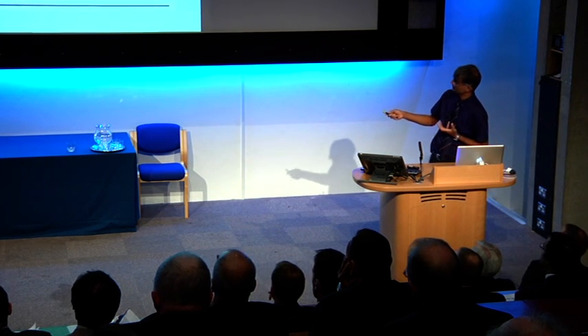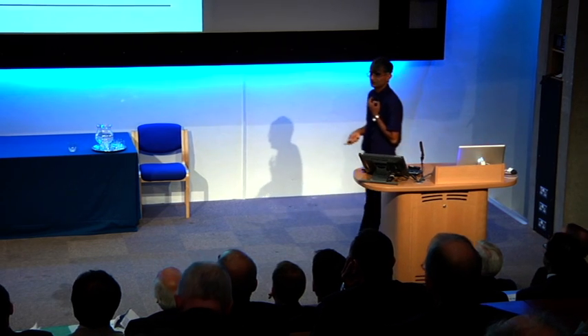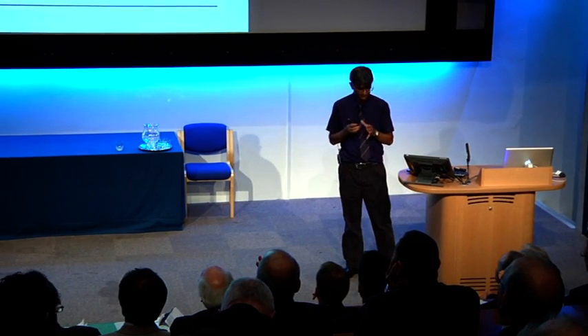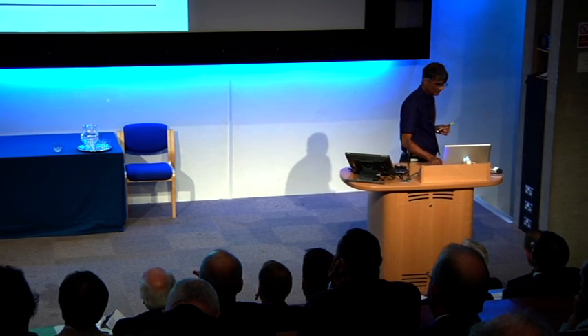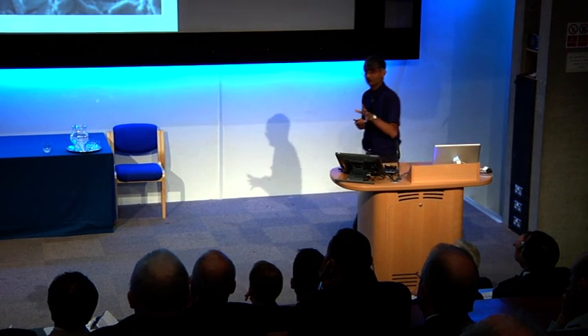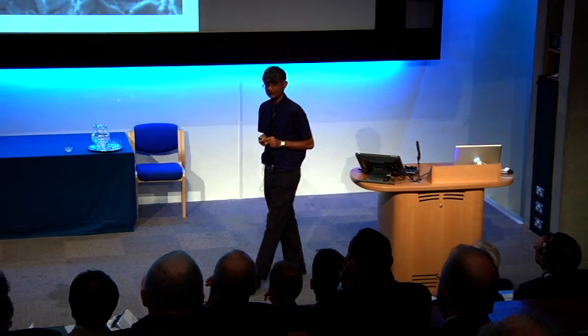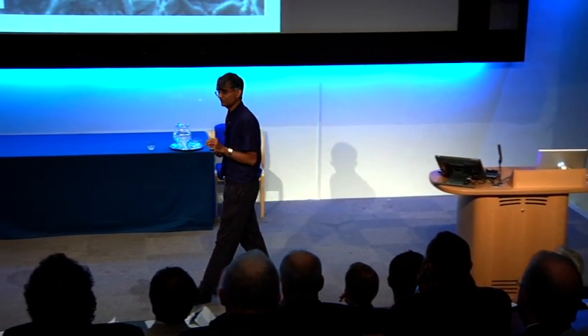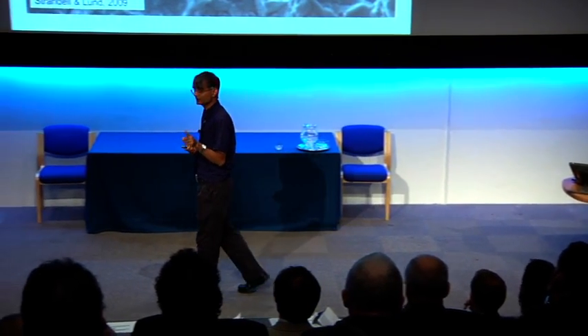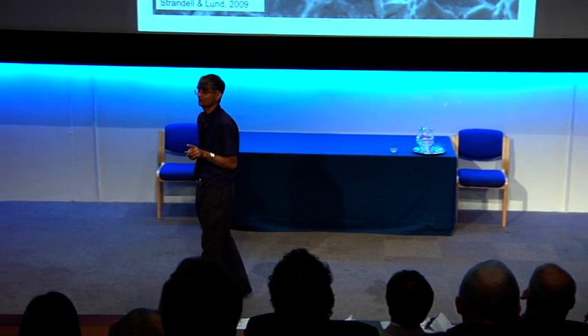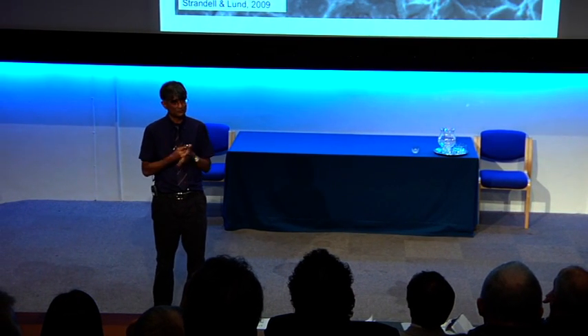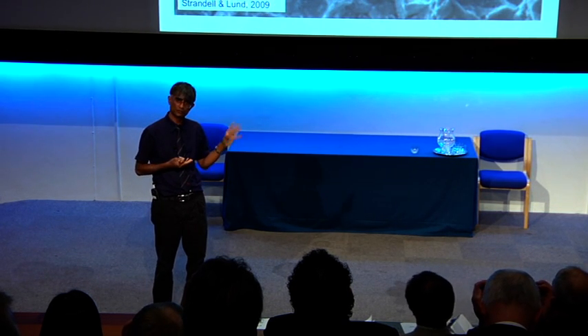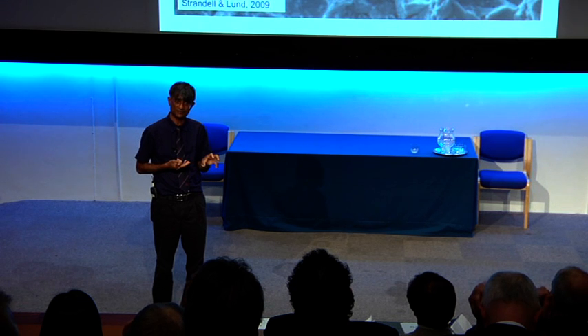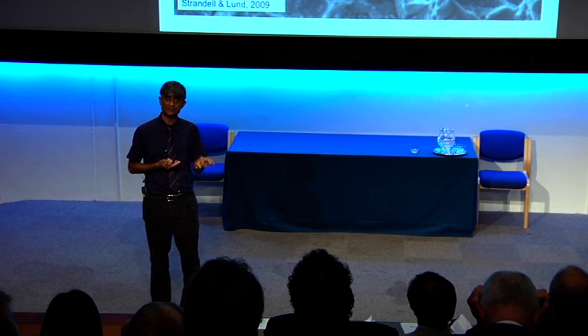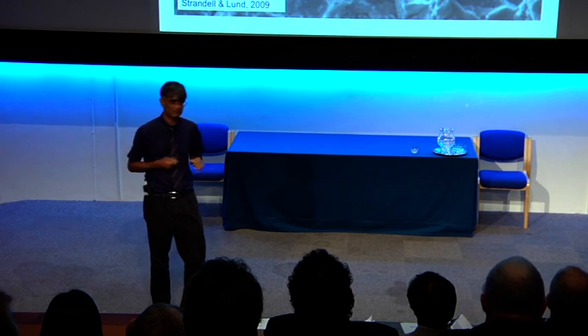So we're probably not going to be able to reduce the phosphorus concentration much in bearing steels, but I think I have seen intergranular failure in bearing steels, which means that we need to strengthen the austenite grain boundaries. Once you get micro cracks at the austenite grain boundaries, you will get damage because of the pulsating stress and white matter, etc. So the role of carbides and of austenite grain boundaries becomes important when we make clean steels with fewer inclusions and so forth.